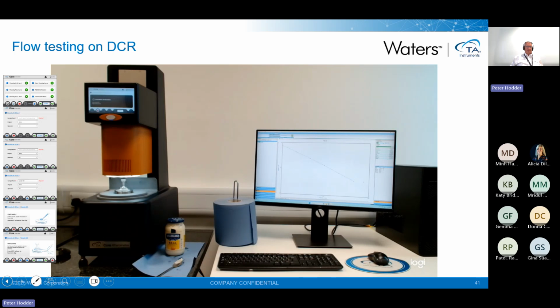Final point, and then our focus will switch back to the touch screen of the DCR, where it will fit the analysis and give us the results on whether it's in spec or not. So what we've got here is it says, congratulations, the experiment is successful. It's given us a prompt to say that at 50 reciprocal seconds, we're within range. We're towards the high end of the range at 5 reciprocal seconds, but we're still in spec.